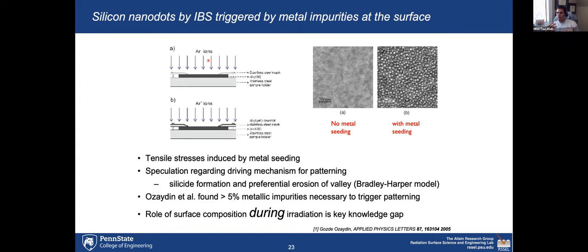And it was an accidental discovery. As they were doing irradiation, they found that the resputtering of the holders of their silicon samples, the metal being resputtered, in this case I think it was moly, those moly atoms arriving with argon in fact led to prompt self-organized structures that formed on silicon. So again, without any kind of impurity or metal contribution, you couldn't get patterns. As soon as you introduce some composition of metal, you got patterns on silicon.